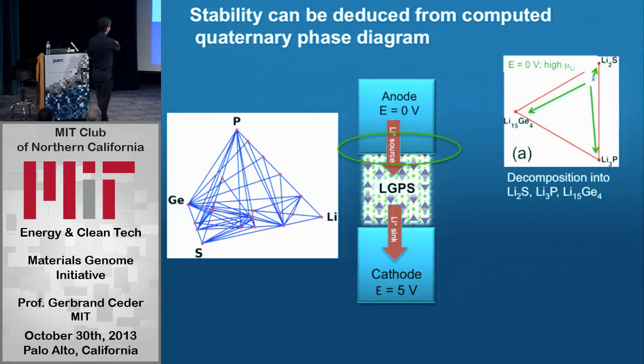But a few other things. Stability, this is really important, right? A battery is an extremely aggressive environment. You're essentially, at one point, at 0 volt, which is where you're roughly metallic lithium-like, and at the other point, you're at 5 volt. And to put that in chemistry terms, that's a 500 kilojoule driving force for a 1 electron reaction. And it's a 1 megajoule driving force for a 2 electron reaction. So basically, almost everything can happen uphill, because you have a megajoule of energy sitting around there if you can move electrons between these two things.